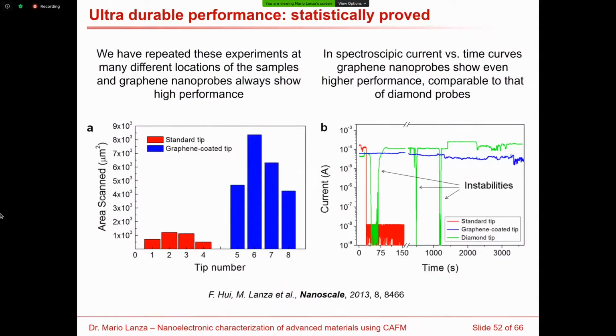We also did these experiments many more times. We evaluate the amount of area that can be scanned without conductivity decrease with standard tips and with graphene-coated tips. And while there is a normal deviation from tip to tip, we observe that all the graphene-coated tips show lifetimes much higher than the standard tips.